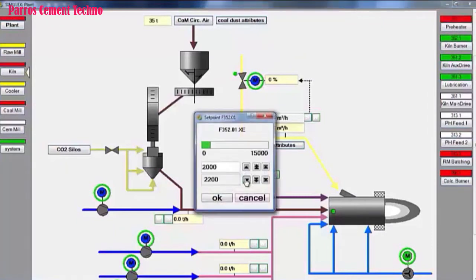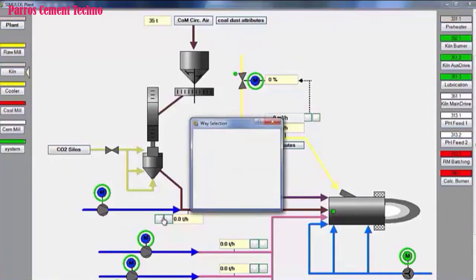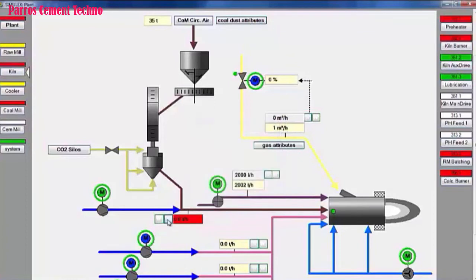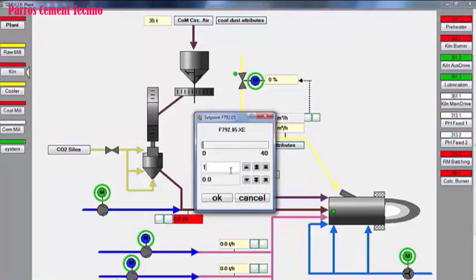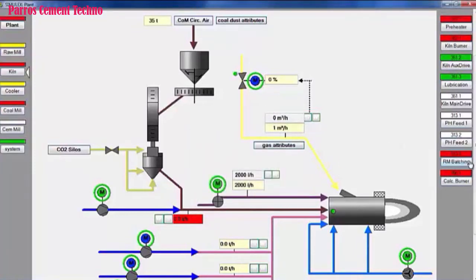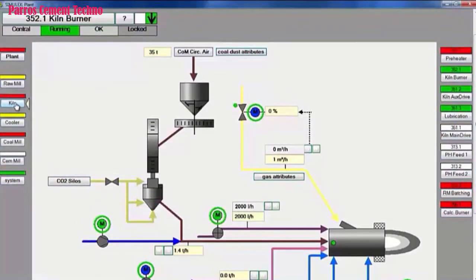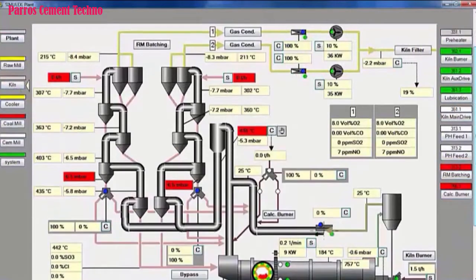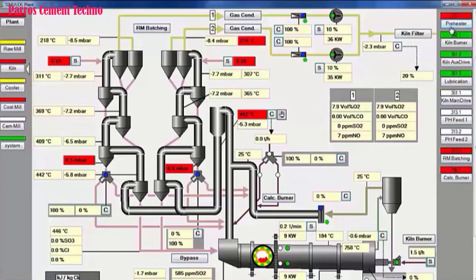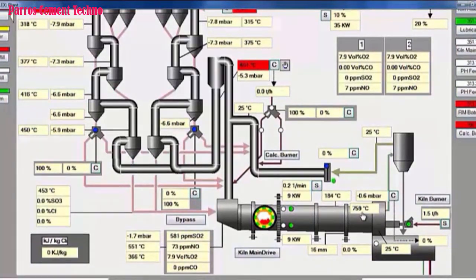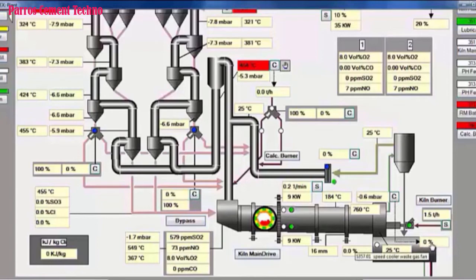We reduce the use of oil from 2200 liters to 2000 liters, or we just set it to 2000 liters per hour. Then for the first use of coal we use 1.5 tons per hour. We return to the display kiln. The cyclone's top temperature rises rapidly, because the ID fan cooler damper is at 0%, so we add the use of cooling air in the cooling fans.